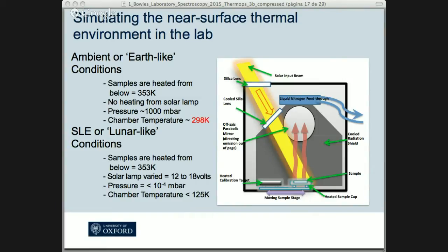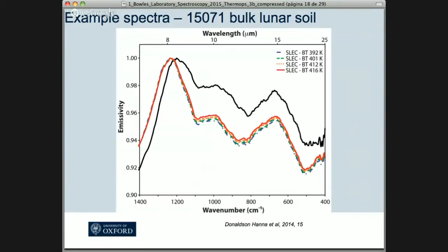So here's an example. We're actually looking at an Apollo 15 bulk lunar soil sample, and this is the effect of changing from an Earth-like environment, the black line, to a lunar-like environment. Again, these are spectra measured by Kerry, and you can see that once you've set up the temperature gradient, it's pretty stable. You get very similar looking spectra, but the key thing is these spectral shifts. But please note, compared to the pure mineral sample, this is actually much more suppressed. We're now looking at changes in emissivity of fractions of a percent, a few percent, no more than that.